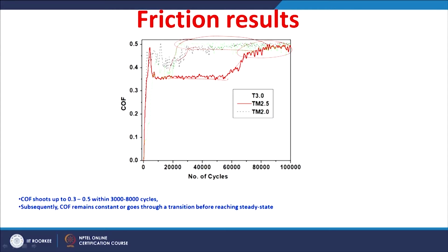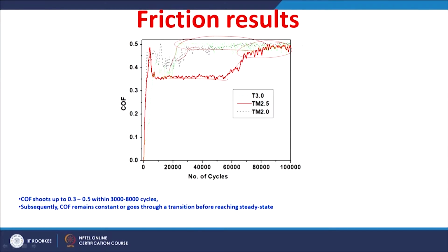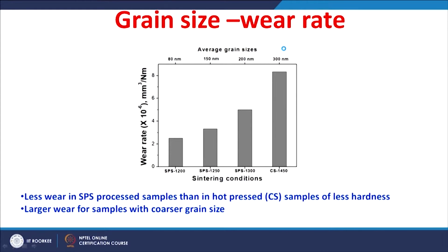So, it indicates that the friction is dependent on the yttria content in this zirconia nanoceramic material. Overall, higher coefficients of friction were obtained for all 3 samples after around 100,000 cycles of this fretting against steel. So, the wear rate was determined.